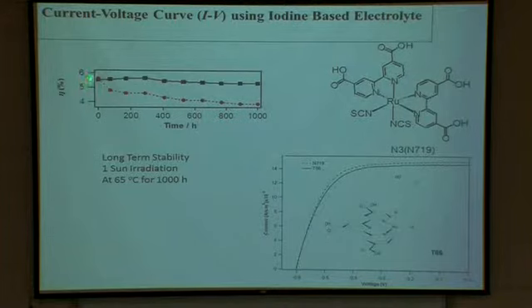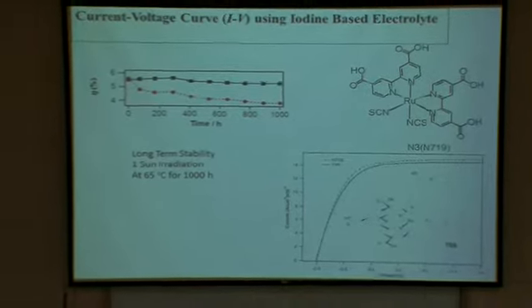As you can see, the efficiency went down from 5.5 for N719 down to 4. Whereas for T66, in the first couple of days it increases, and then it goes down by only 7%. So at the end, 93% of the initial efficiency was retained. So this is the first part.